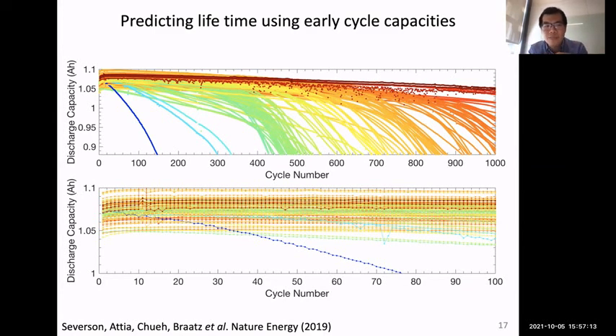Where you're looking at the top here is the degradation of the battery capacity, the coulombs it is able to store as a function of the battery charging and discharging cycles. The goal here is, can you look at the first tens or 100 cycles and predict the performance at the end of life? In other words, whether this particular battery is going to last a long time or a short time. So naturally, we can zoom into the early life of the data. That's the bottom plot. I'm showing the first 100 cycles. This is zooming into the left 10th of the data on top.